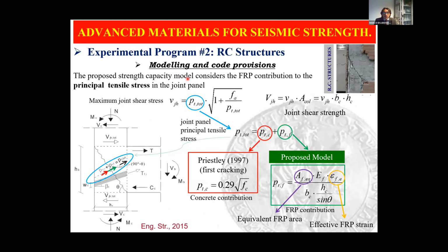So, exactly as before, then we moved on to the possibility to design this strengthening solution and to compute the real contribution of FRP. So we proposed a strength capacity model which considers the FRP contribution to the principal tensile stress. So the idea is to compute how much FRP can contribute to the maximum joint shear stress, which depends on the joint panel principal tensile stress. And this value can be considered as the sum of concrete contribution, which is the first cracking, given by the very well-known formulation provided by Priestley. Then, since no stirrups are inside, we use FRP to contribute to close these cracks, to sustain this action.